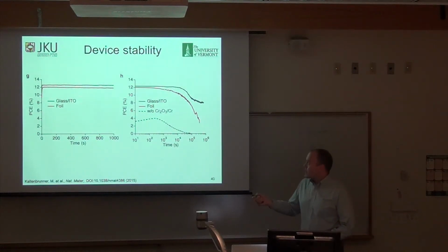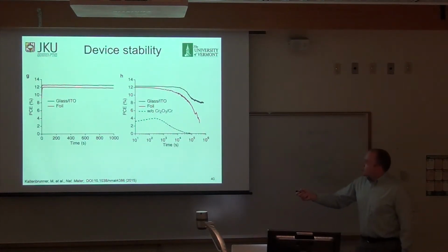So this is the best way to really characterize power. We just let that run over the course of a day or two, under continuous operation with absolutely no encapsulation. We make the devices, take them out in the lab, and put them under the solar simulator, and they can operate for a day of continuous operation before decaying to 80% of their power generating capacity, which is remarkable. If you take this same device without chromium oxide and expose it to air for 10 seconds, it already loses, let's say, 70% of its power generating capacity, and then it dies within an hour completely.